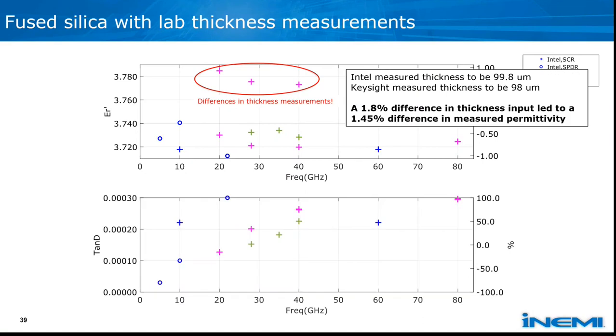Really what I'm trying to highlight here is that if we add in additional thickness measurements from one of the labs, with just about a 1.8% difference in the measured thickness—not even 2 microns difference—we're getting about a 1.5% difference in the measured permittivity just from that. So these thickness measurements do have a tremendous impact on our extracted microwave properties, even though they're not the most exciting problem to address.